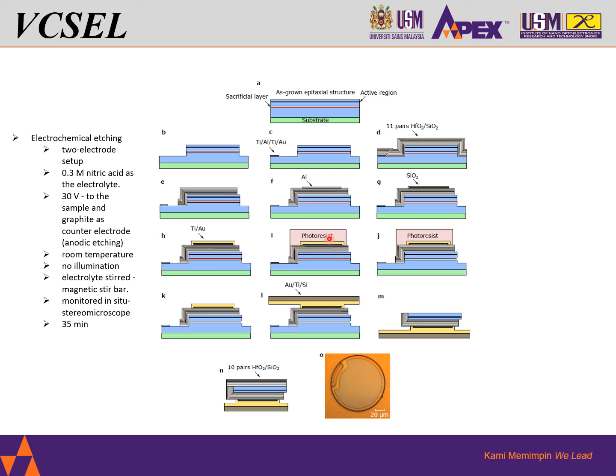And I is the photoresist to protect this layer for the following electrochemical etching. And then J, as you can see here, the sacrificial layer is gone. So this etching actually was done by using a 2 electrode setup using 0.3 molar nitric acid as an electrolyte. A constant positive potential of 30 volts was applied to the sample relative to the graphite counter electrode, leading to anodic etching. The etching was done at room temperature with no intentional illumination, and the electrolyte was stirred using a magnetic stirrer bar. The progress of etching was monitored in situ using stereo microscopy, and the etching of the mesas was completed in around 35 minutes. As a result, you can see here the sacrificial layer was gone.